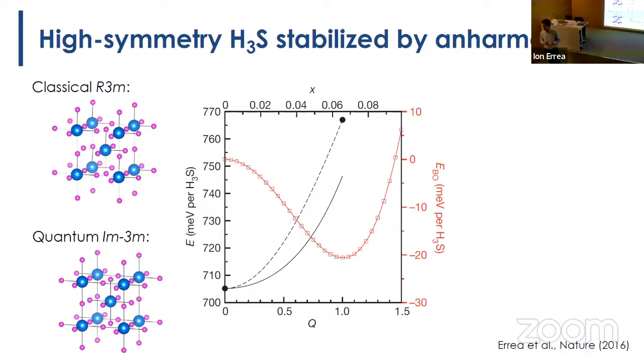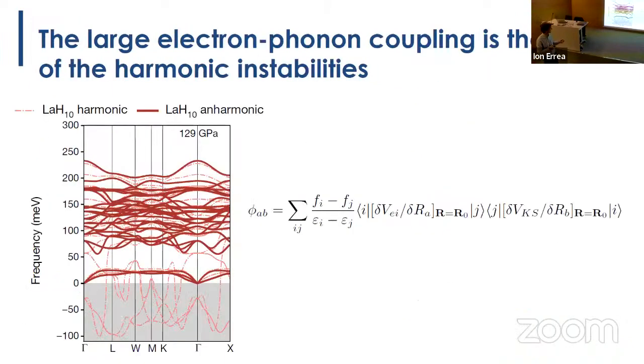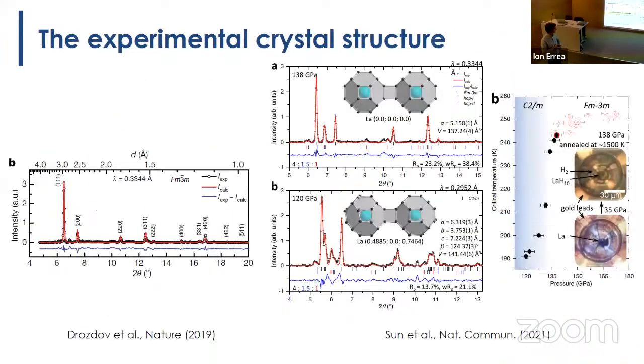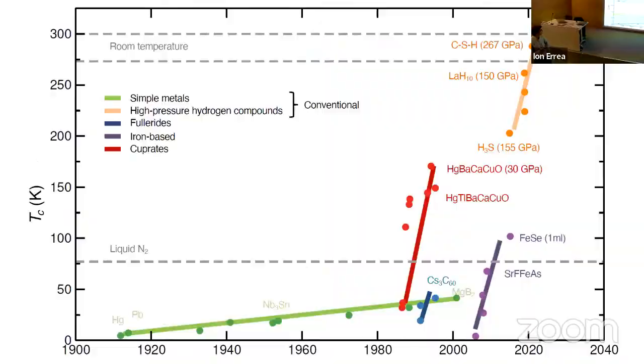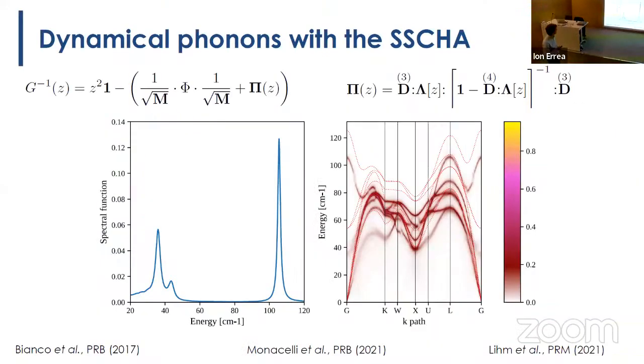How does your approach deal with phonon lifetimes? Because if they are harmonic, then they are not interacting. So do you have to take a next step to be able to do this? Yes, I said that. This is the dynamical extension of the theory. I went very fast on that. Basically, we can calculate this Green's function, the displacement correlation function, which is what you measure experimentally with inelastic diffraction experiments. So this is a dynamical theory. Here we can plot the spectral functions, and these are the lifetimes of the peaks, if you want. So we can calculate these lifetimes perfectly.